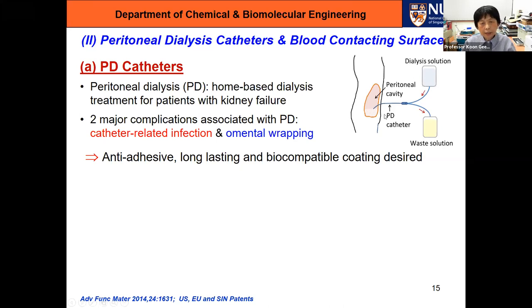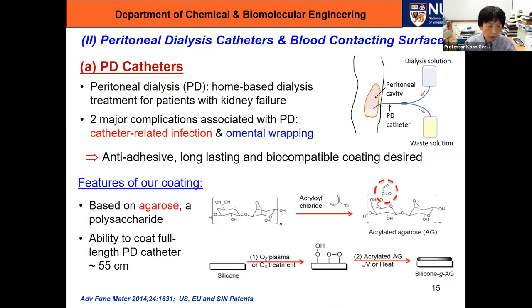Now, because this catheter has to be in the patient for life, we need something that's long-lasting, an anti-adhesive to stop the omentum from wrapping. So we decided to explore agarose, which is a polysaccharide. The way we did it is to first introduce acrylate groups onto our agarose. And then again, we are using silicone as a substrate because that's what the peritoneal dialysis catheter is made of.